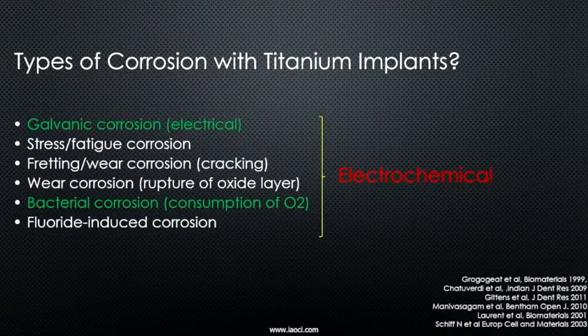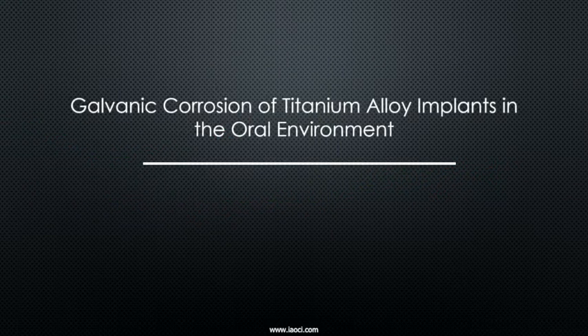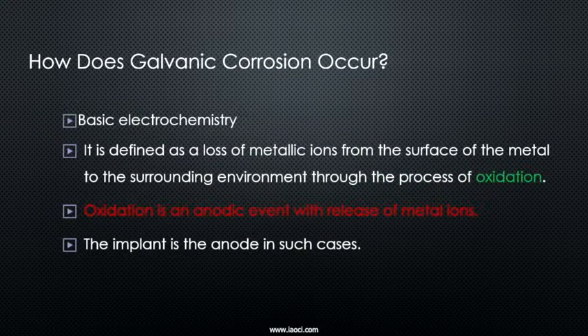So we have certain types of corrosions on titanium implants, on metal implants. We have galvanic corrosion. We have corrosion that stems from fatigue and stress, from wear, from bacteria. There's such a thing called bacterial corrosion. And there's also fluoride-induced corrosion, good old fluoride, right? And all these phenomena are electrochemical in nature. So let's look at galvanic corrosion to start with. It's electrochemistry. It is a loss of metallic ions from the surface of the metal to the surrounding environment. Okay? So it's an anodic event with release of metal ions.